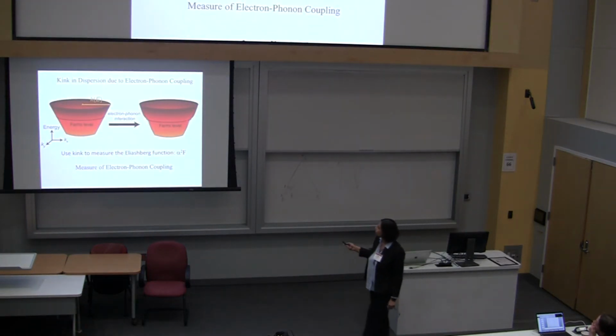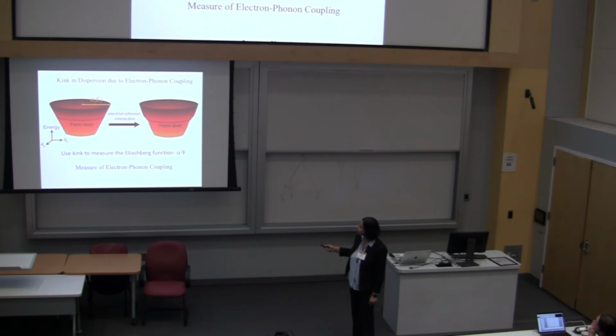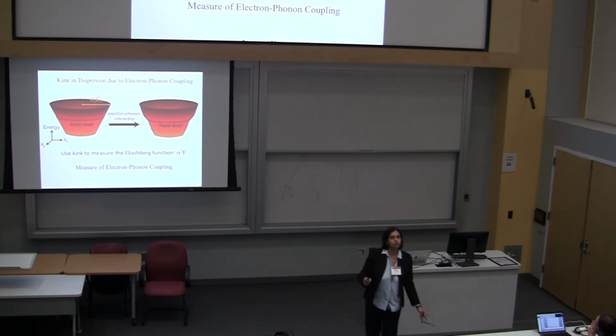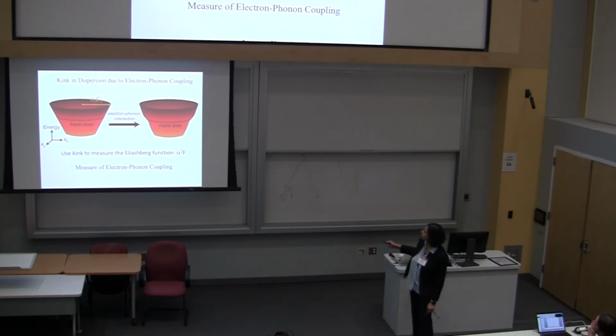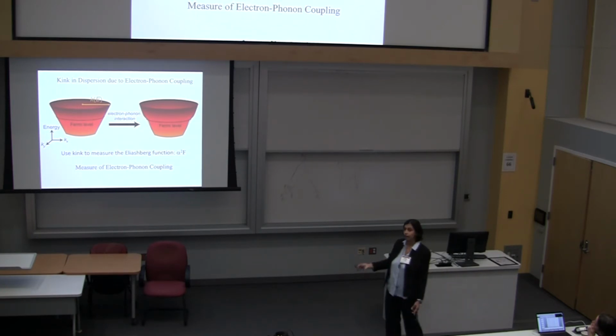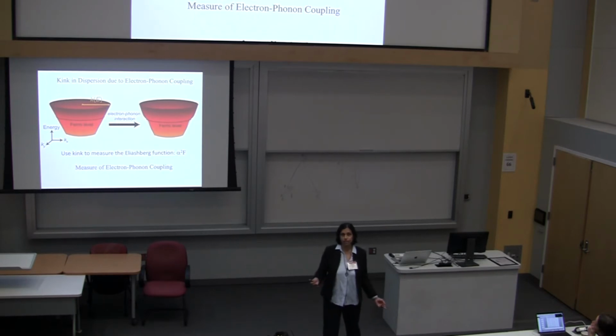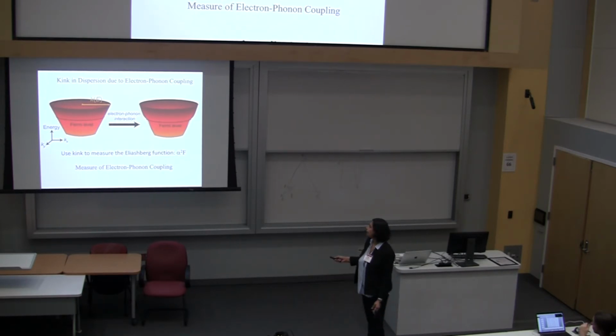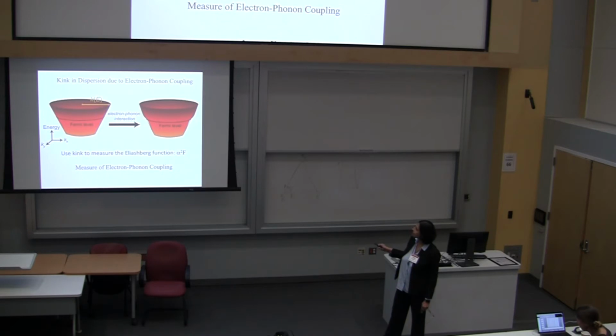So remember what electron-phonon interactions give you. Here's just a parabolic band, right? This is in 2 dimensions. Here's the Fermi level. If you turn on electron-phonon interactions, this is just Ashcroft and Mermin, what you expect to see is the dispersion as you go across the Fermi level develops a small kink. That's all the effect of the electron-phonon interaction is, if it's not very strong. If it's very strong, you'll get a charge density wave or a superconductor or something. So you can use this kink.